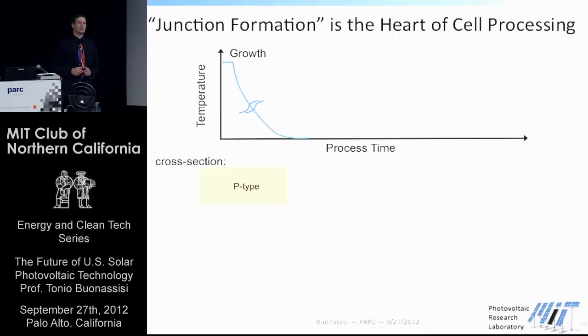Right, so I told you about the time temperature profile, your oven, if you will, that you use to process your solar cell device. Silicon is like a rock, and to get it to do anything, you really need to either use some powerful chemicals or high temperatures to move atoms around inside. So to grow the material, we melt it at around 1400 degrees C and then cool it to room temperature and wind up with a wafer.